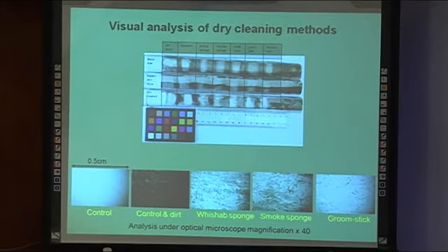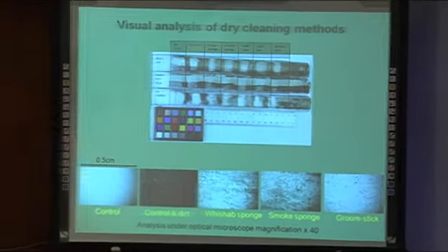This is just an example to show my method where I did the cleaning tests on the artificially soiled samples to see which ones were most effective and also to see what effect they had on the treatments applied. And then underneath is where I chose the most effective methods and then viewed them under an optical microscope to see the damage to the surface of the plaster.